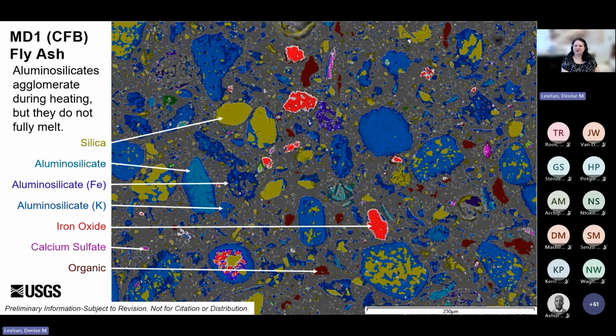Note that gray here is background, so it's the space between the particles. Silica is this kind of olive color here. And then we have aluminosilicates in blue with different other element concentrations, like the inclusion of iron and potassium as different shades of blue. We also have these red iron oxides and purple calcium sulfates that are formed in the CFB boilers, specifically with either that addition of limestone or limestone within the original coal to trap that sulfur dioxide gas in a mineral form, as opposed to it going to a scrubber emissions control. So the calcium sulfates are basically sulfur not forming sulfur dioxide gas that escapes. And then there's some small pieces of residual organic matter coal that's this brown color.